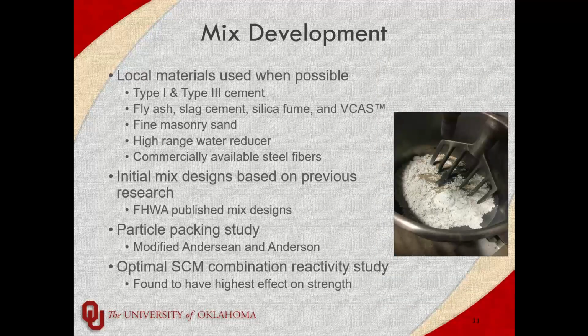So as I said, local materials whenever we could, and unfortunately we weren't able to, but the mix development process took about 1.5 years total. We went through a number of different mix designs, but we used mainly type 1 and 3 cements. The supplementary cementitious materials we focused on were fly ash, slag cement, silica fume, and vitrified calcium aluminosilicate. It's a product that Vitro Minerals produces.